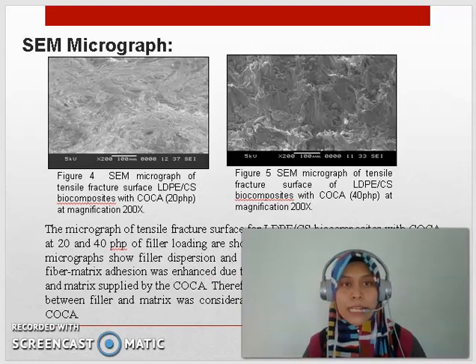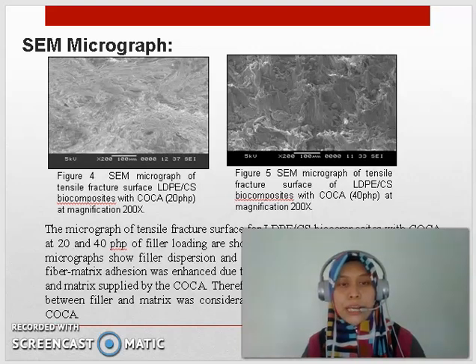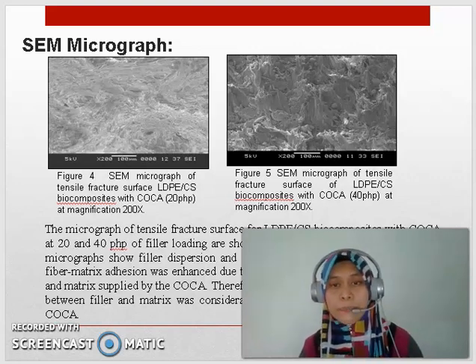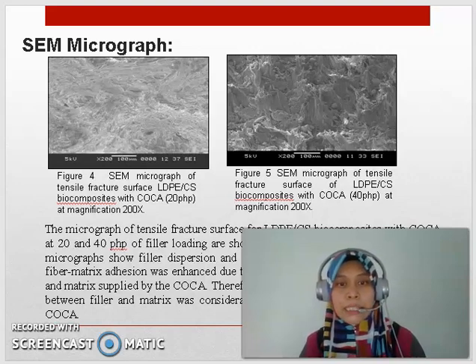The last one is about SEM micrograph. Figure 4 shows the SEM micrograph of tensile fracture surface of LDPE or CS biocomposites with COCA at 20 php at magnification 200x. Figure 5, SEM micrograph of tensile fracture surface of LDPE or CS biocomposites with COCA at 40 php at magnification 200x. This result shows that both micrographs show filler dispersion and adhesion is better in the LDPE matrix. The fiber matrix adhesion was enhanced due to the chemical connections between fiber and matrix supplied by the COCA. Therefore, these results proved the compatibility between filler and matrix can be considerably improved when reacted with COCA.